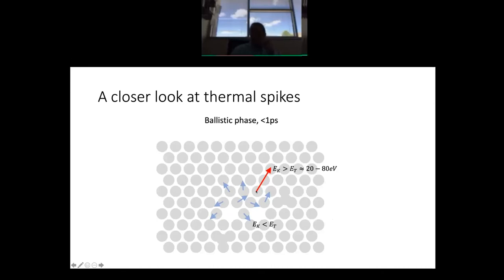So if an atom happens to receive a kinetic energy that's above the threshold, and in addition to that, it happens to be aligned with the closest packed crystallographic direction, which in the case of face-centered cubic materials is a 110 Miller index type direction. In a body-centered cubic material like alpha iron, it would be the 111 direction. Okay, if that happens, then you initiate something that's known as a replacement collision sequence.